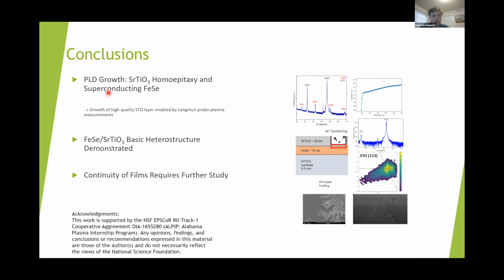So in conclusion, we demonstrated through pulsed laser deposition that we can grow strontium titanate homoepitaxially on its substrate, as well as grow superconducting iron selenide. And this is enabled, obviously, by the Langmuir probe I initially showed that helps us prevent the oxidation of the iron selenide. And iron selenide and strontium titanate heterostructures were demonstrated, where we could see the growth of epitaxial strontium titanate as well as epitaxial iron selenide with a crisp, sharp interface between them. So there is no mixing between the layers. And then we also demonstrated that the continuity of the films can vary based on the incidence of the plasma ions onto the substrate, and that this incidence will require further study to determine where the islands become continuous.